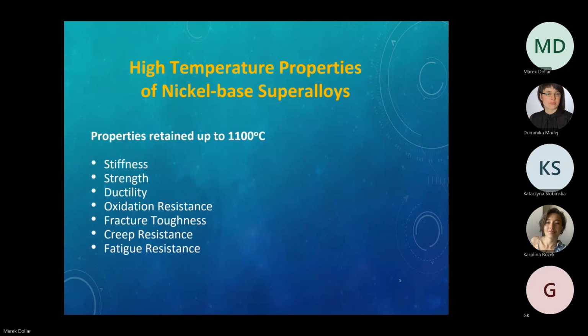Just one slide. I mentioned 1100 degrees C. Nickel-based superalloys in their single crystalline form offer you excellent behavior in the elastic region, so material stiffness, and in plastic, and now we are talking about plastic deformation, they're strong and ductile. That's the combination that we need for structural materials. The oxidation resistance is good, and they have particularly excellent creep resistance, which is of major concern. But also the fracture toughness is great, and fatigue resistance is good.